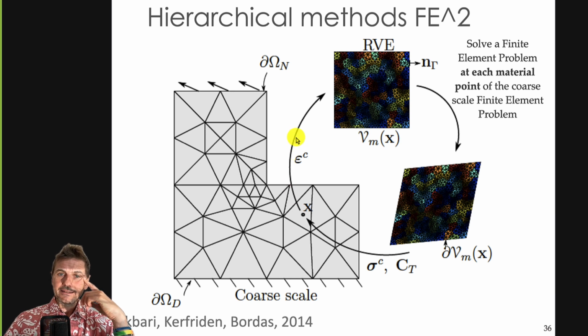So the idea is that you do not assume anything about how sigma depends on epsilon, except based on how the microstructure looks like. You no longer have a functional form that gives you sigma c equals function of epsilon c. What you have now is a whole partial differential equation in a quite complex domain that is being solved, and that gives you sigma c and the tangent stiffness every time you pass epsilon c to the RVE, which is done at each integration point in each element of the coarse scale finite element domain.